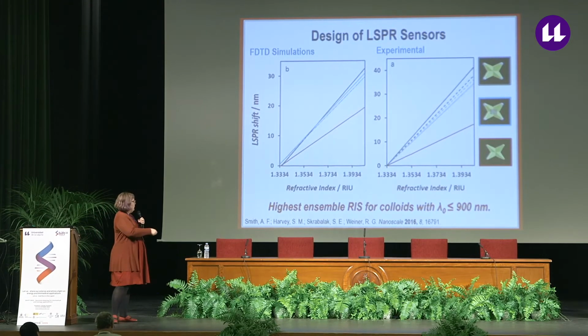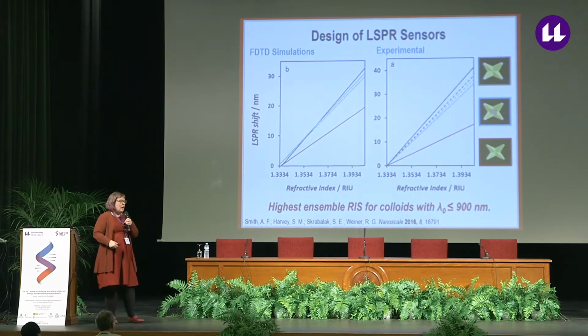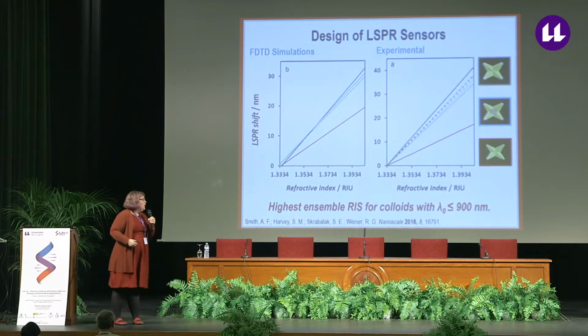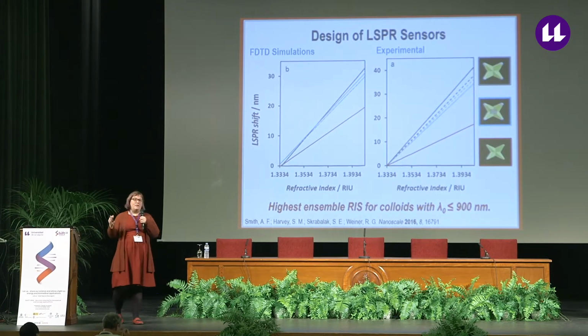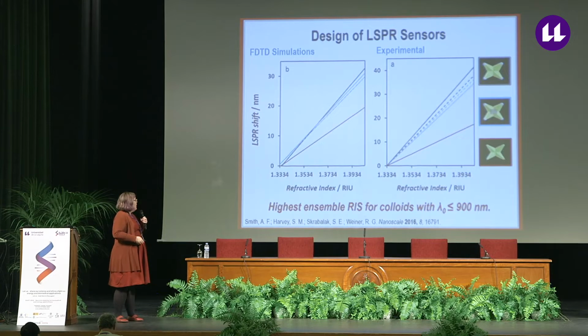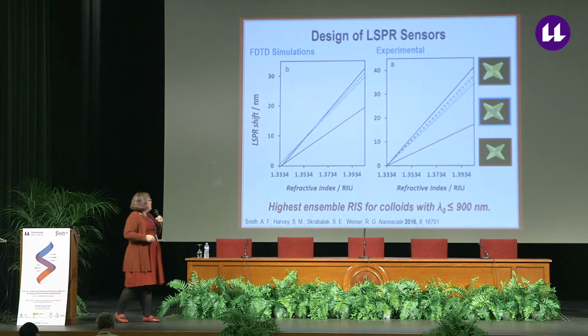So at the time that we reported this, we had the highest ensemble refractive index sensitivity for colloids with an initial wavelength below 900 nanometers. I think it has recently been beat out by other palladium gold systems. But